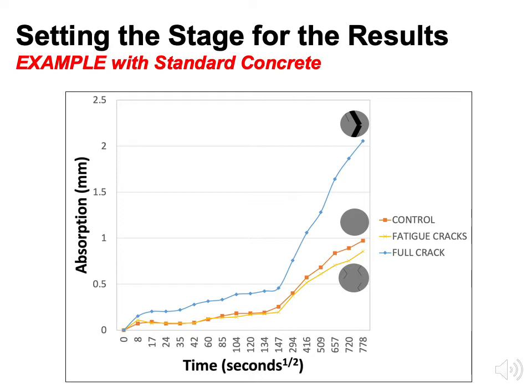And as you can see, with the fatigue cracks, we're not getting as high as a primary or secondary absorption. It's actually similar to the control. And we attribute this to exposing some hydration kinetics. We're not creating true cracks. We're creating percolation that over time will densify and absorb water for the benefit of the concrete, as opposed to the full crack where we're absorbing enough water that we have almost like a super absorption, or a storage of water that is not being used for absorption of broken or fractured particles, as well as cement hydration. All right. So again, this was shown as an example with standard concrete in this image, this data set. We haven't applied the EDYSTON, but let's get into that.